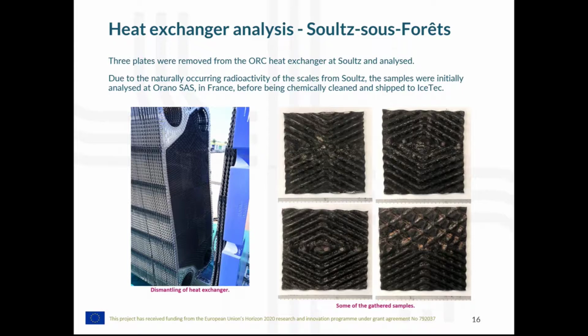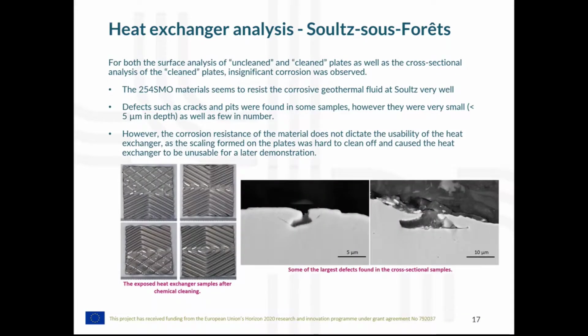So after analysis at Orano, all the scales were removed chemically, and also the corrosion products, and then shipped to Iceland for further analysis. So we analyzed both uncleaned and cleaned samples, the surfaces, and then we did some cross-sectional analysis here in Iceland. And we observed insignificant corrosion on the 254 SMO plates, which seems to resist corrosive geothermal fluid quite well.